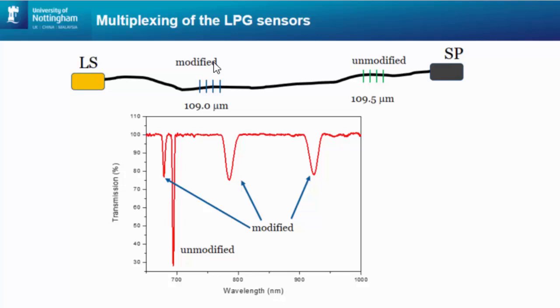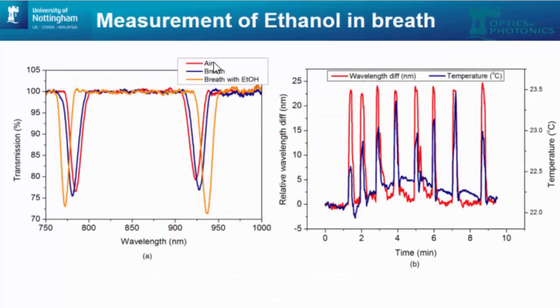So what we did with this sensor, we did a breath test. So we measured ethanol in breath, and the experiment was very simple. So we had a couple of drinks, and then measured the response before and after alcohol consumption. So you can see a change in the transmission spectrum here. So air, the breath without the presence of alcohol, and breath with the presence of ethanol.